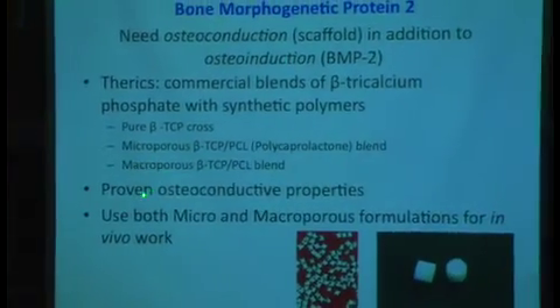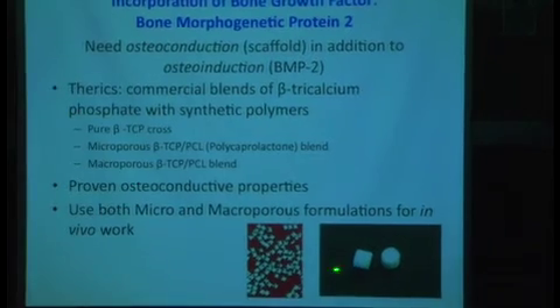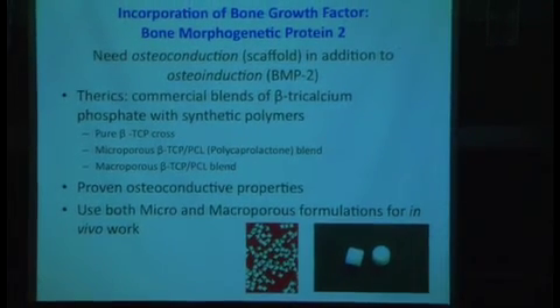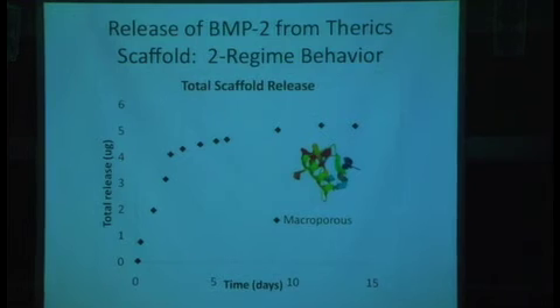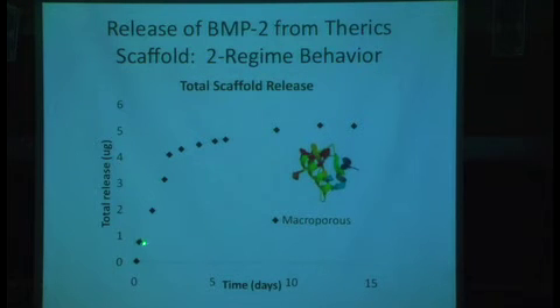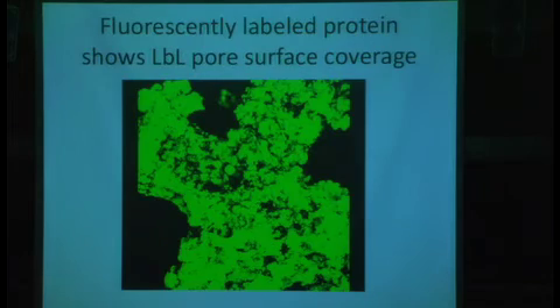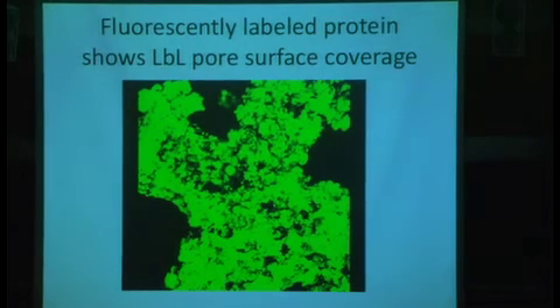In the work related to the orthopedic implant, we're working with bone morphogenetic protein 2, or BMP2, and we're using an osteoconductive scaffold, which is just this beta tricalcium phosphate 3D printed. It's from Therics. It gives us the ability to coat a very high area, and we can use our spray layer by layer technique to do so. We get a release which is fairly rapid over the first 3 to 4 days, and then a sustained release after that. We get very nice conformal coating of the implant.